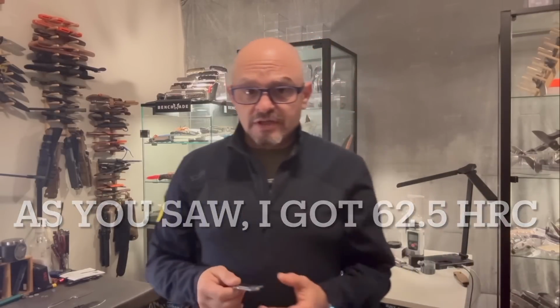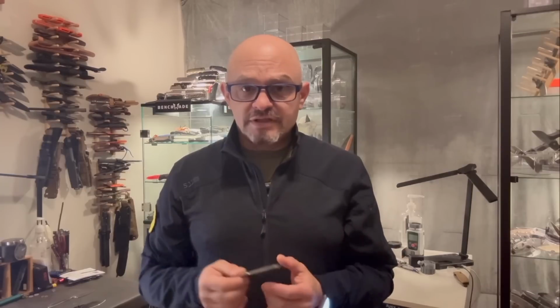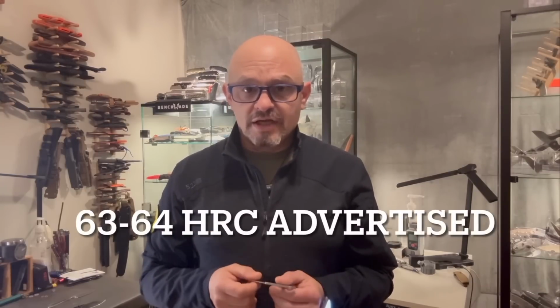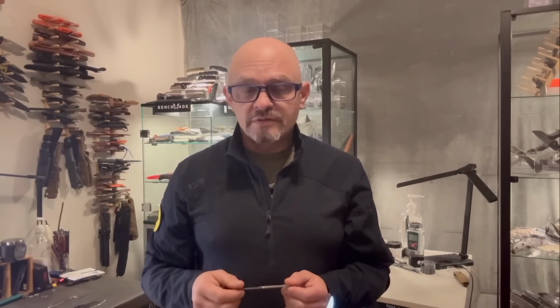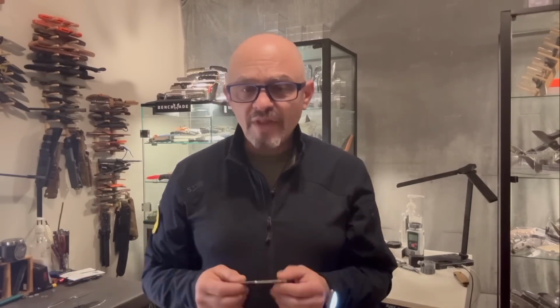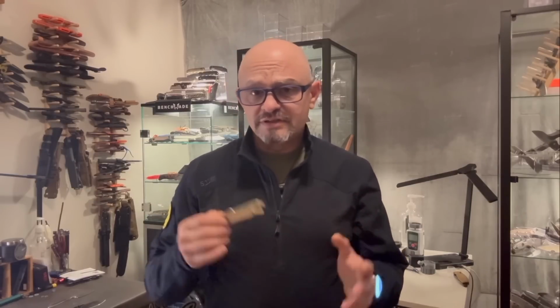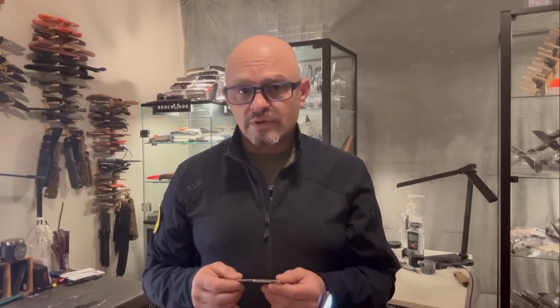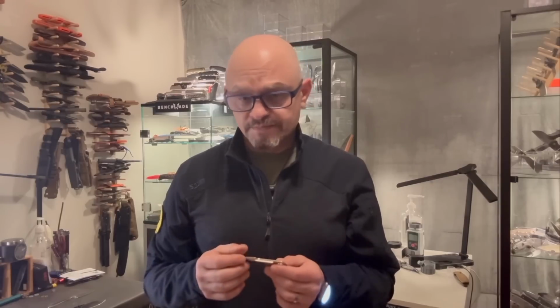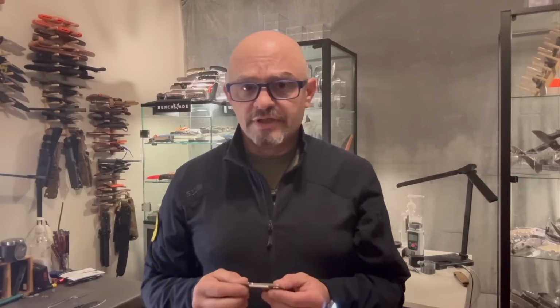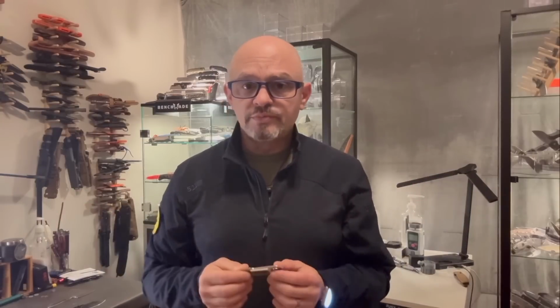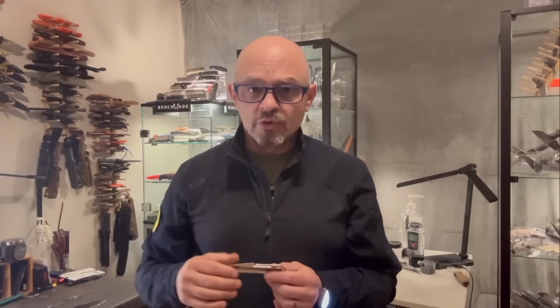Does it mean that the whole batch of knives that came from Bestech has softer than advertised heat treat? Not yet. The batch, from what I understand, was about 400 knives. A batch that size requires a test of at least 20 blades. So I don't think we can declare that all of these knives are going to be at the bottom or below the advertised range based on these 5 samples.